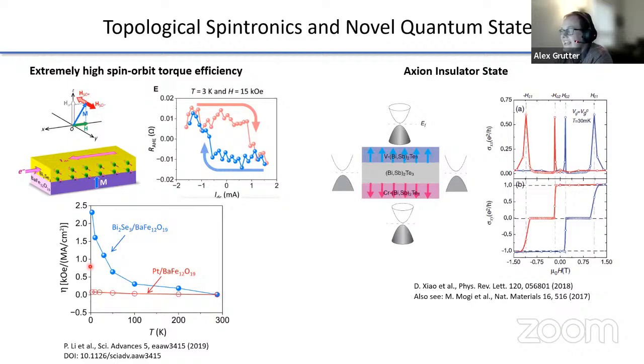Yes, so in both cases, it appears that the chromium selenide is insulating, so far as we can tell. There doesn't appear to be, at low temperature, metallic shunting of the current from the topological insulator through the chromium selenide. And so we think the surface state is still there because the chromium selenide appears to be insulating. But of course, we have not seen the quantum anomalous Hall effect. So if you want to strongly argue that it doesn't exist, I will not be able to prove otherwise.